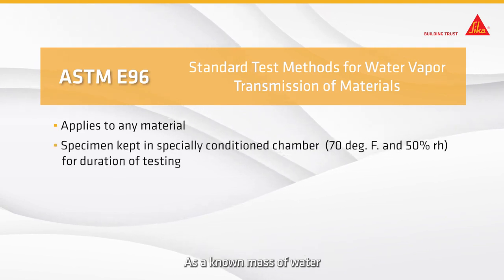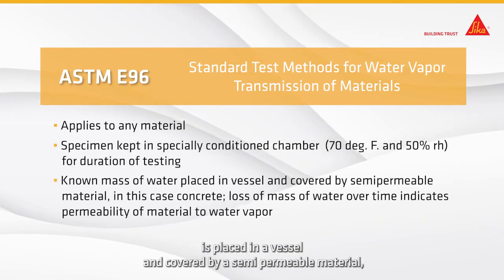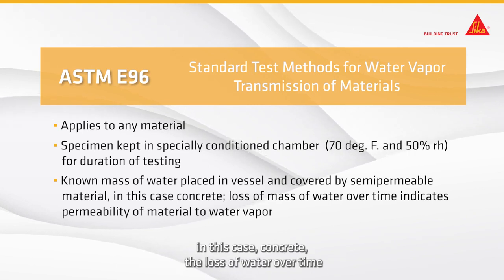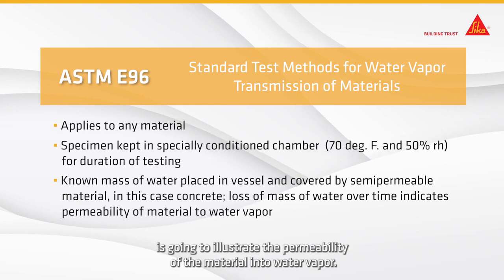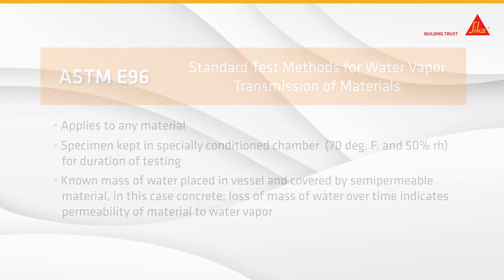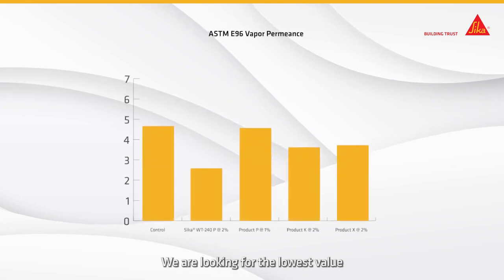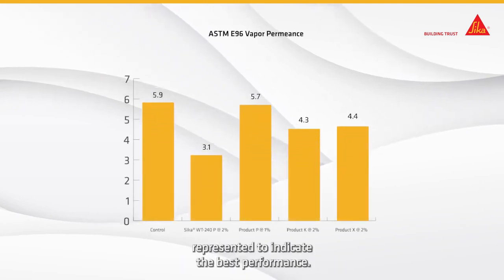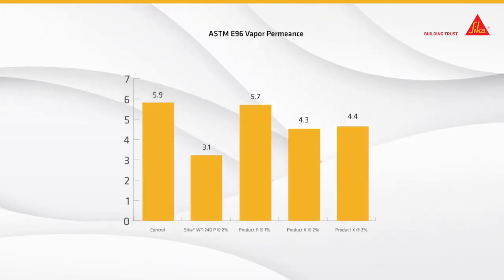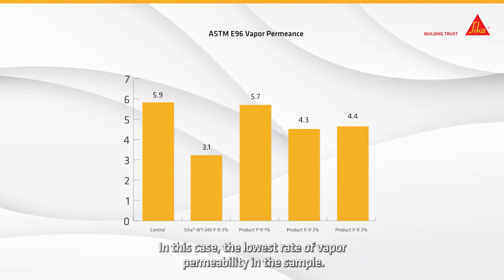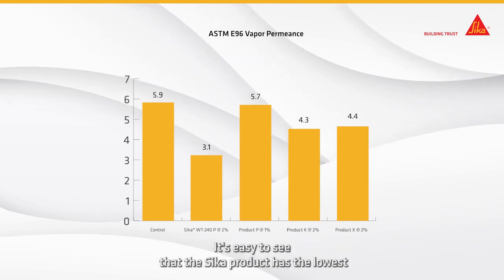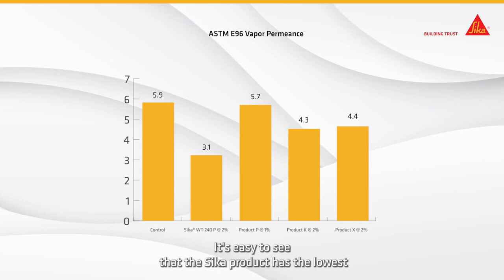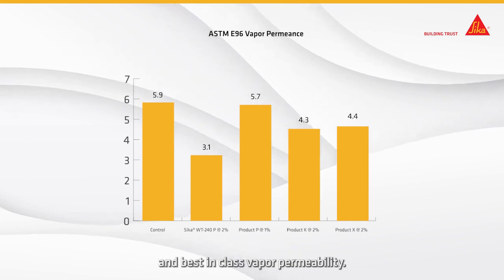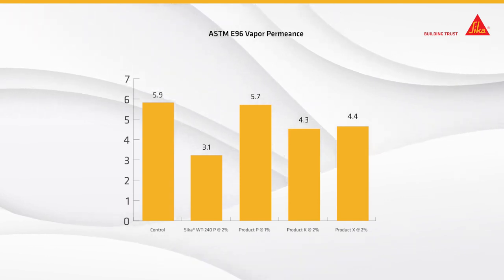As a known mass of water is placed in a vessel and covered by a semi-permeable material, in this case concrete, the loss of water over time is going to illustrate the permeability of the material into water vapor. We are looking for the lowest value represented to indicate the best performance. In this case, the lowest rate of vapor permeability in the sample. It's easy to see that the Sika product has the lowest and best-in-class vapor permeability.